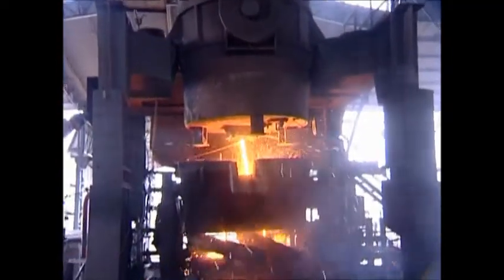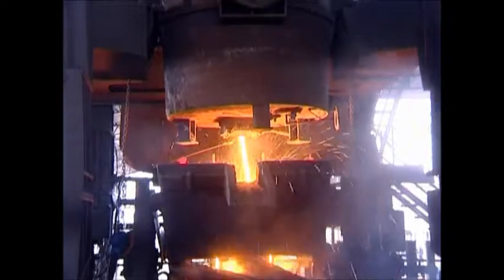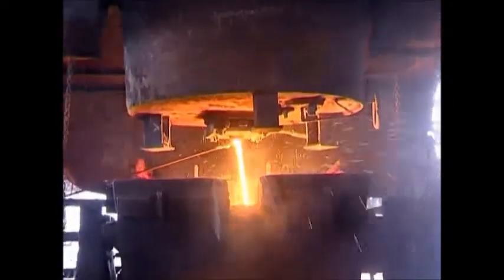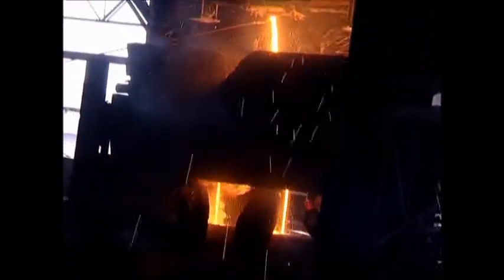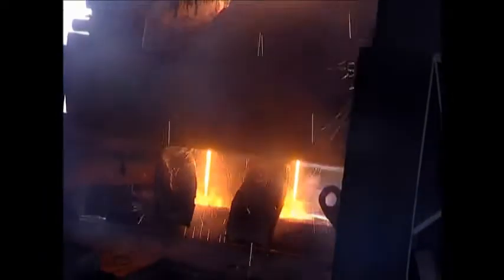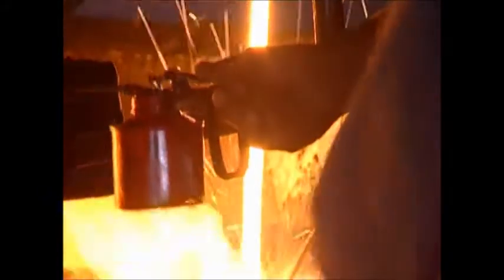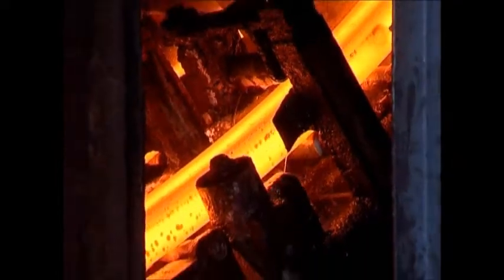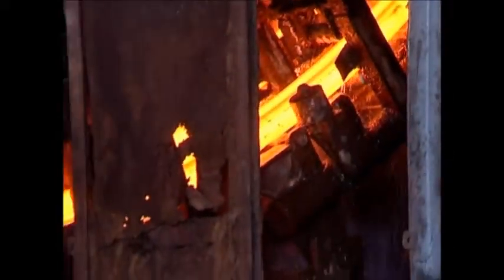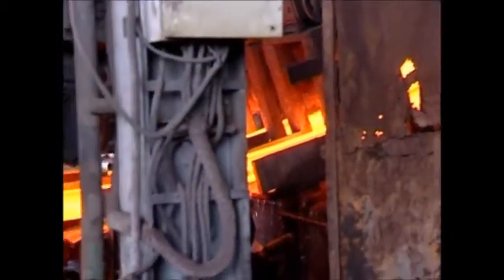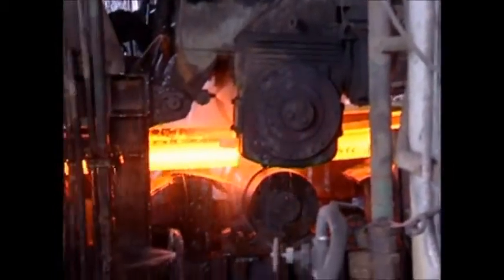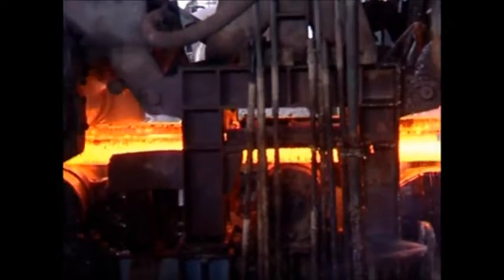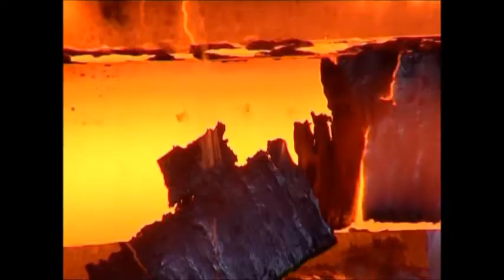A mechanical jack opens the slide door of the ladle and the liquid metal starts pouring into the tin dish. Then the liquid metal passes through two different continuous copper molds from two nozzles, and after passing through the two molds, the process of water cooling takes place with the help of water spray nozzles. Liquid metal is finally converted into solid metal billets of 100 by 100 and 120 by 120 mm size as required.